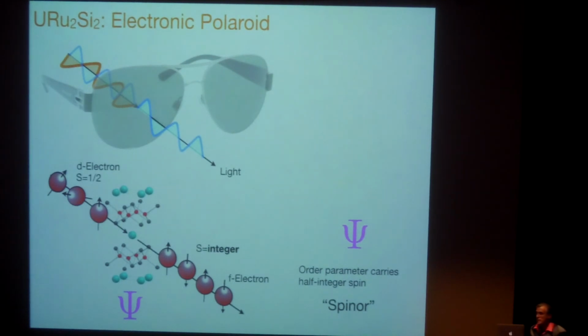Yeah, so I think there's a furious debate in the field, and one idea is that when you're at a quantum critical point, you get soft fluctuations. Those provide the glue, and that drives the pairing. I think it's a very prominent idea. Another idea, which would be the other extreme, would be that you release the spin degrees of freedom, which have been bound up inside the antiferromagnet, and they're now available to entangle as you would like. And that entanglement now drives, amongst other things, superconductivity.